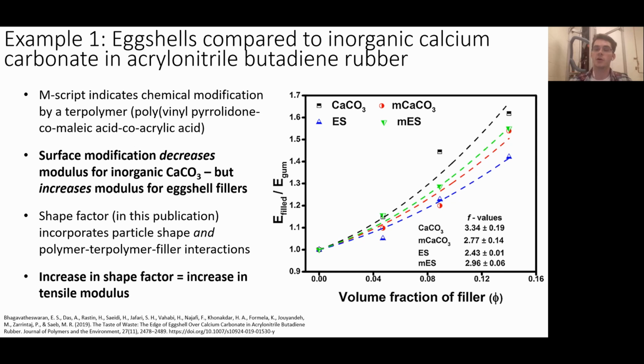So they applied Guth's model and used a shape factor to fit their Young's moduli. It's kind of interesting here, they used shape factor to incorporate those polymer, terpolymer, and filler interactions here. So it's kind of a fudge term. It basically accounts for a lot of microscale mechanisms that are going on in these composites. But the conclusion here is that an increase in shape factor results in a faster increase in tensile modulus with your volume fraction of filler.